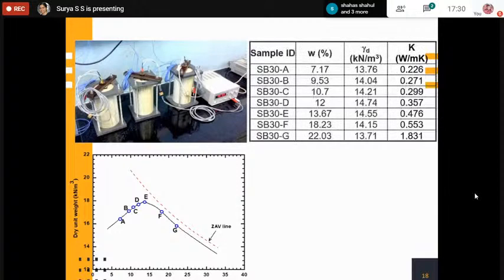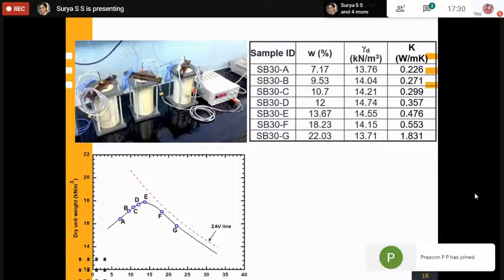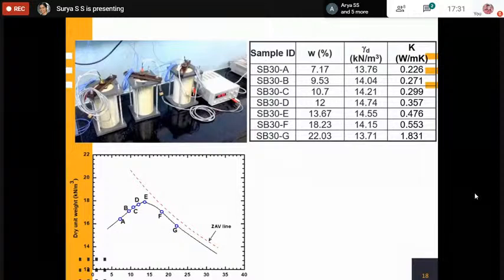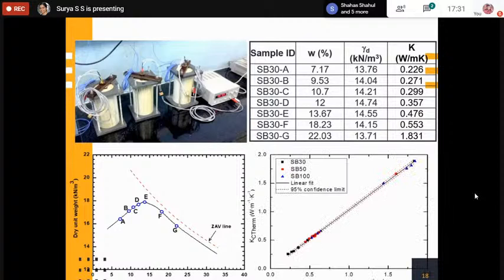This table shows the thermal conductivity values obtained for SB30, that means a sand bentonite mixture with 30% bentonite content. A to G represents the water content or the position on the compaction characteristic curve. And here you can see that the thermal conductivity value is increasing as the water content is increasing. So this means that when we add water, there will be a thin film developing around the soil particles that bridges the small gap between the soil particles, and this will ensure more heat flow and thus result in more thermal conductivity. So from this graph, the thermal conductivity values obtained from the probe and that from CTherm.